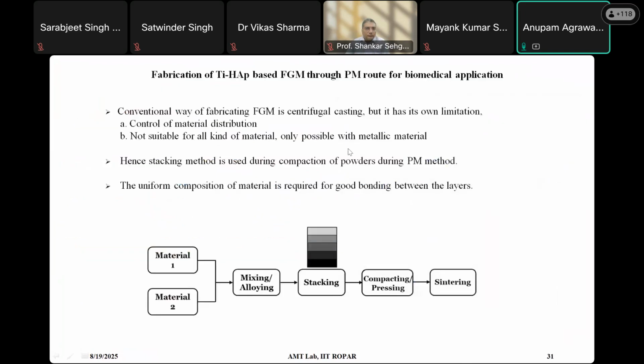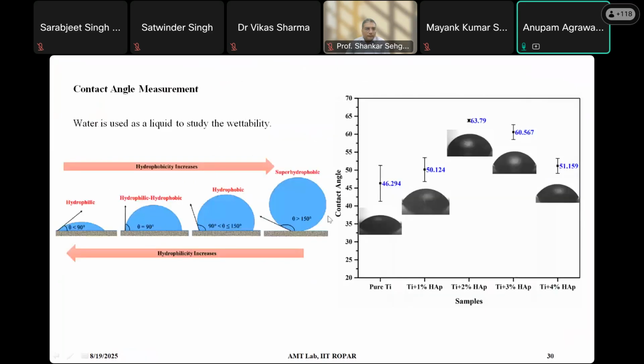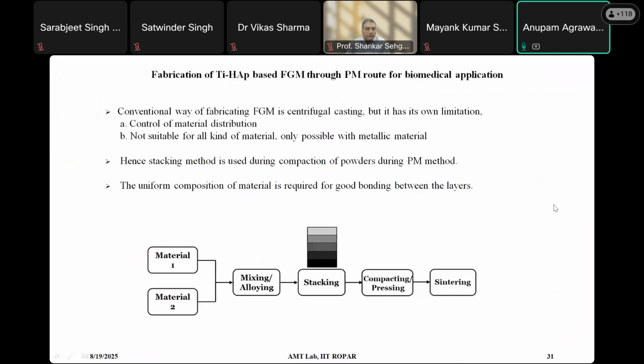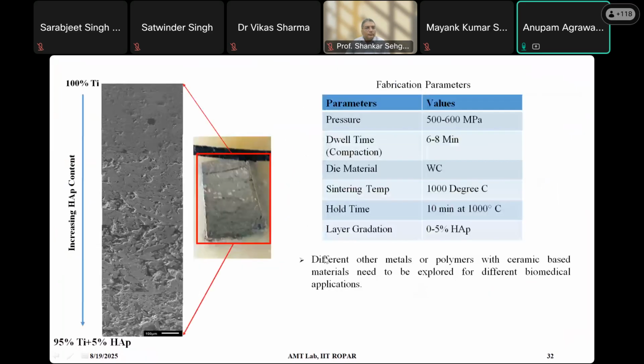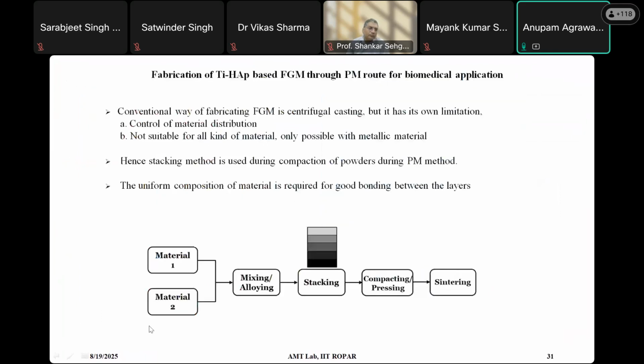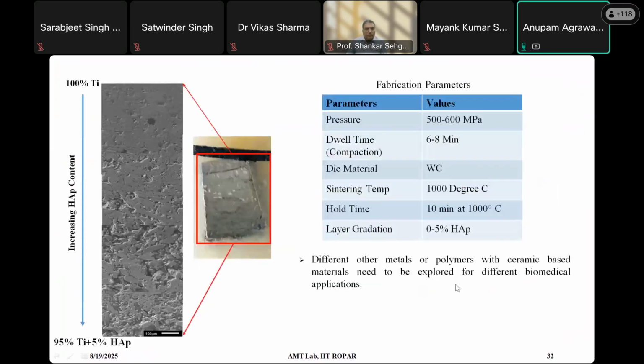So we thought, let's try making not just a solid sample of equal density, but also a varying density sample. So with this mixing, alloying, and stacking, we start with 100% titanium at one end, going to 95% titanium and 5% HAP. So that kind of variation. We stack the different layers with different compositions, press and compact them, and then sinter it to make this sample. Now, fabrication of this FGM was a challenge.